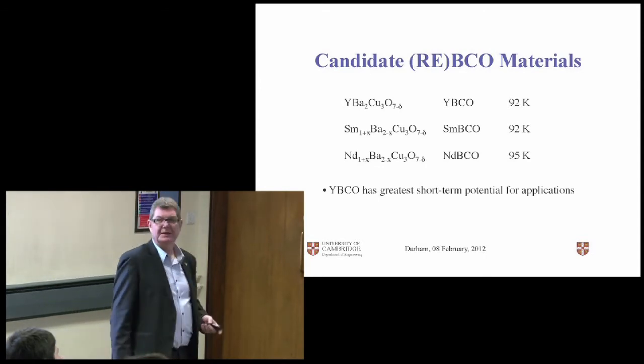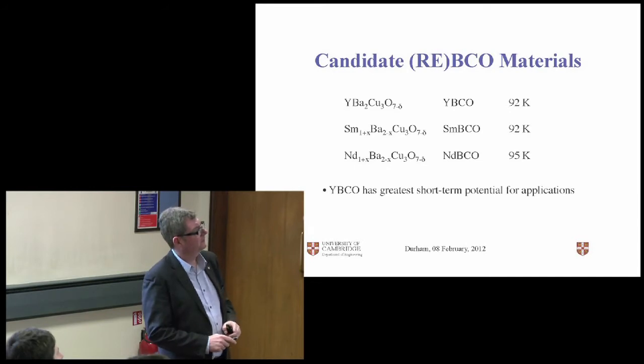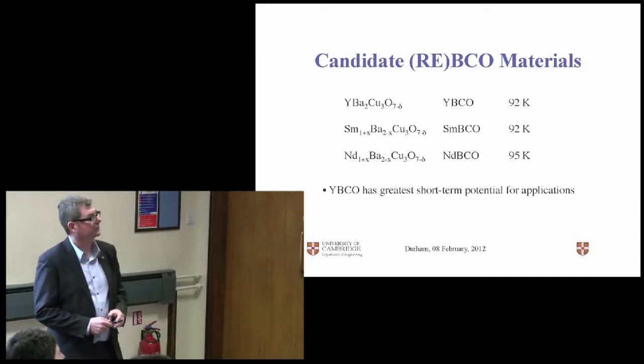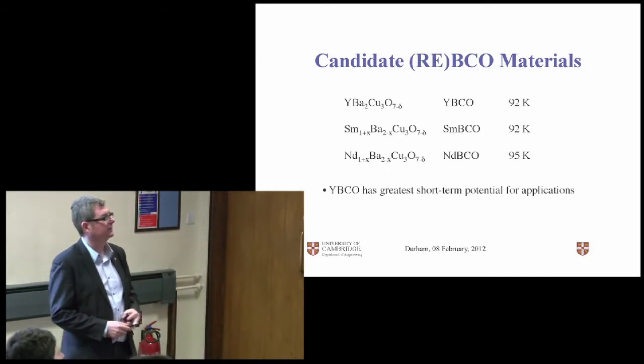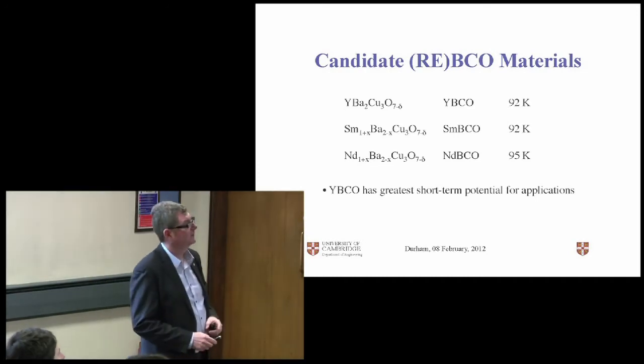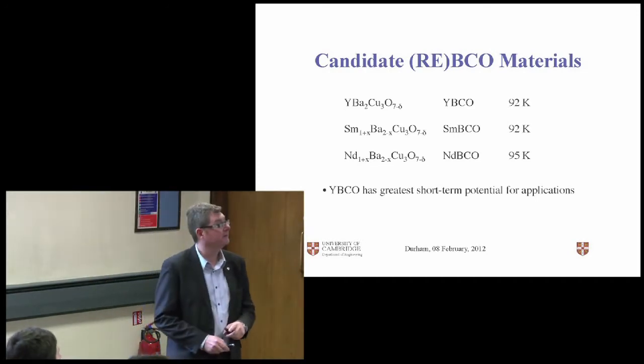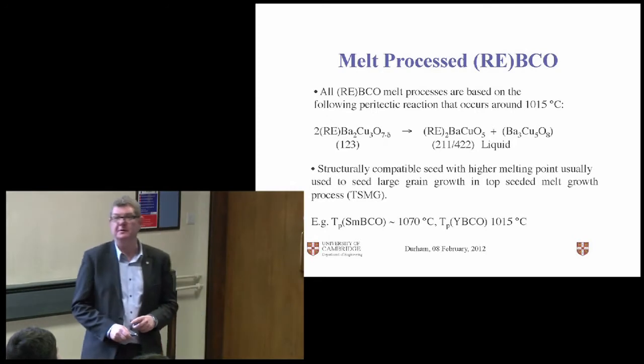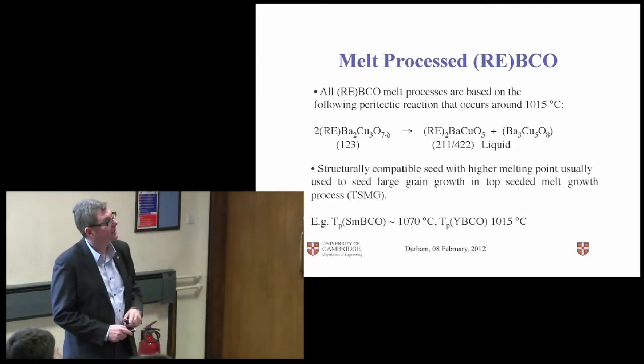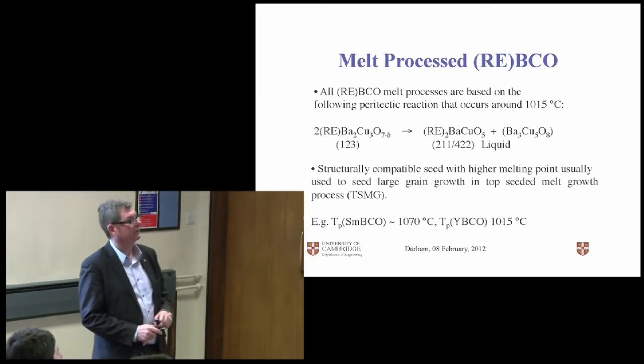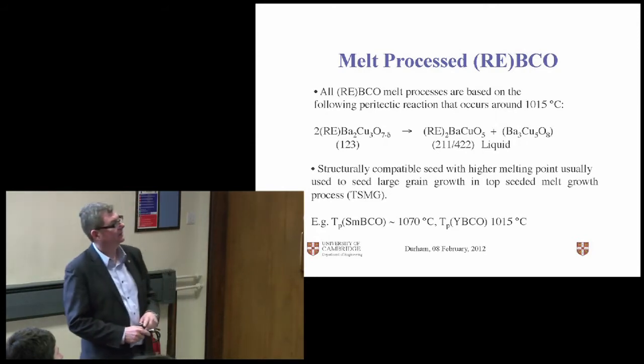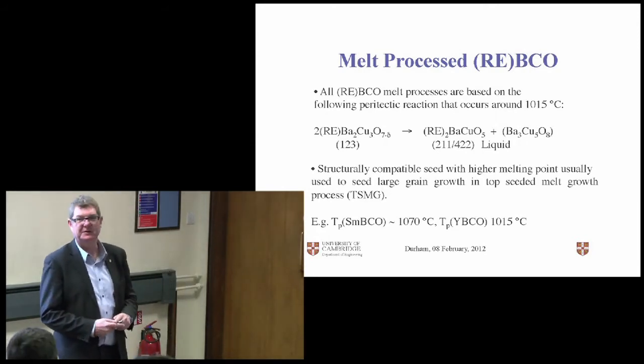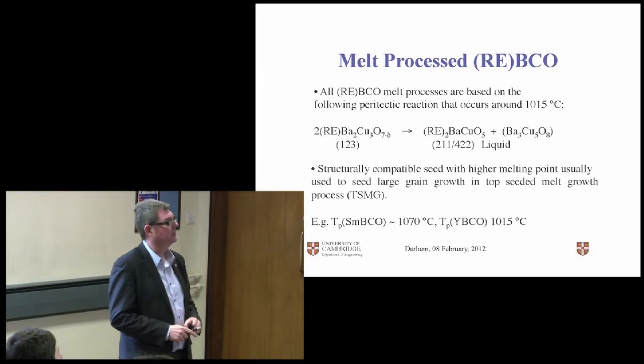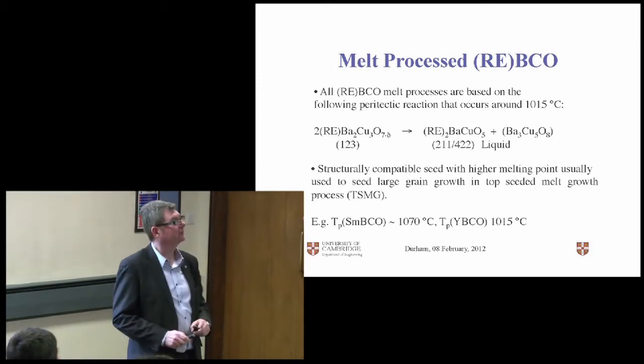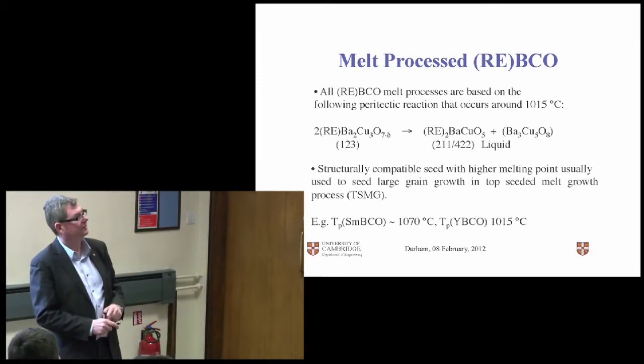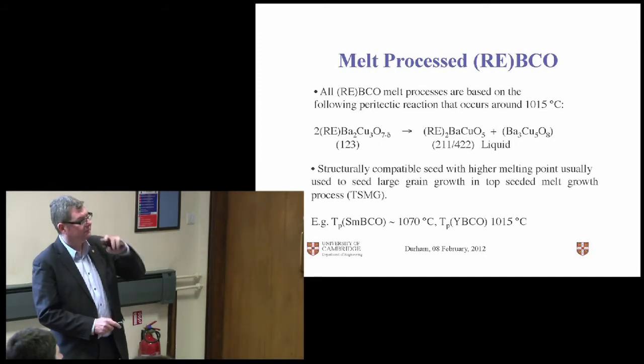Okay, so how do you make rare earth barium copper oxide? Well, this is quite neat. I went to a lecture at Cambridge, a second-year materials lecture on teach yourself phase diagrams, and the lecturer said there's no known use for a peritectic reaction, practically. These materials are based on a peritectic reaction, so this is probably the only useful peritectic reaction. Some say there is a peritectic reaction in steel making that's useful, but whether that's true or not, I don't know. So what's a peritectic reaction?